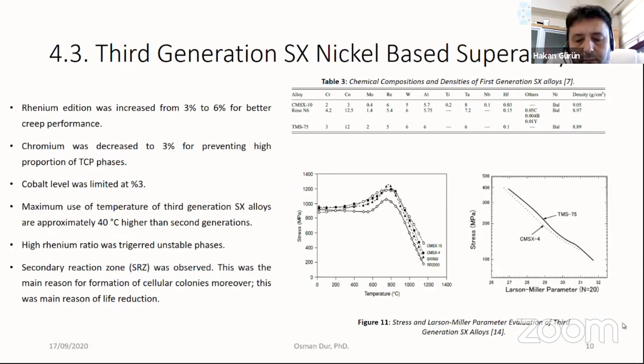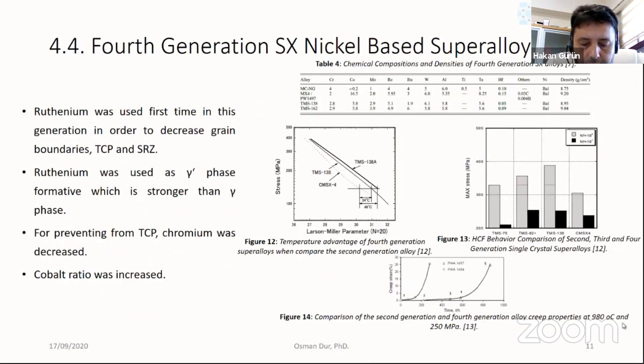As you see in the figure, CMSX-10 is better than second generation alloys for strength. TMS-75 is another third generation alloy which has better Larson-Miller parameters than second generation CMSX-4. Ruthenium was used for the first time in this generation in order to decrease grain boundary TCP and SRZ. Ruthenium was used as a phase former, which is stronger than gamma phase. For preventing TCP, chromium was decreased. Cobalt ratio was increased.